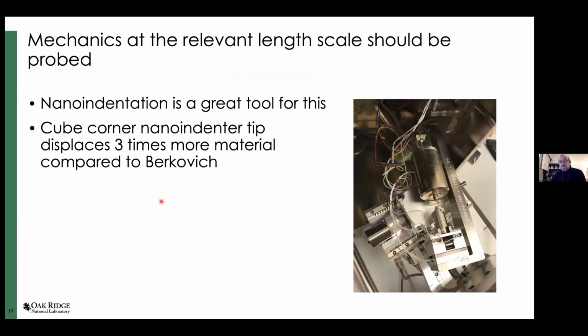Thank you. So yeah, these properties need to be investigated at the relevant length scales, so that a comparison of apples to apples can be made. And the relevant length scale is again the length scale of those lithium filaments that we see, or the defects in the materials. So that's from a fraction of a micrometer to tens of micrometers, probably, for relevant solid electrolytes. And nanoindentation is a great tool for this. This is just a snapshot of the nanoindenter that I use inside the SEM. Very convenient system. You can see what you're doing right away with the electrons.